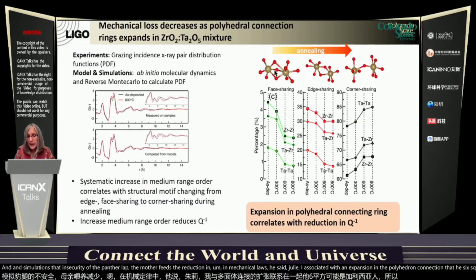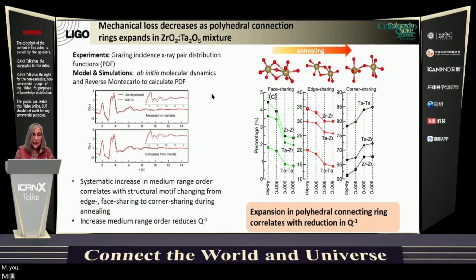So he, using grazing incidence X-ray pair distribution functions and modeling these, showed that there is a decrease in the population of face share and edge share polyhedra, and an increase in corner share polyhedra when the amorphous oxides are annealed to below the crystallization temperature.